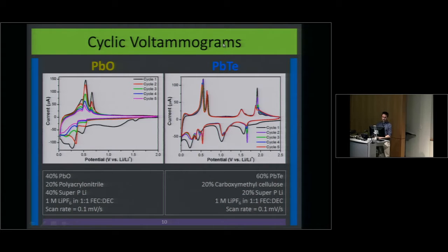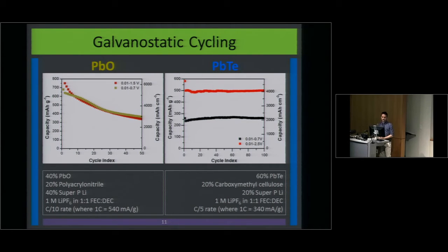We can actually see this more easily if we look at galvanostatic cycling. For the lead oxide, we cycled it at a pretty slow rate where we charged it in 10 hours and discharged it in 10 hours. The lead telluride we did a little more intensely at 5 hours charge, 5 hours discharge. That's what these C rates here down at the bottom are. So C over 10 corresponds to 10-hour charge, 10-hour discharge, and C over 5 is 5-hour charge, 5-hour discharge.